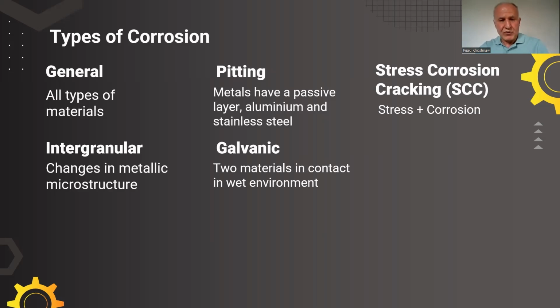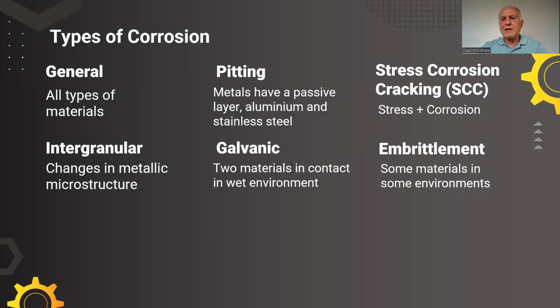Galvanic is a very popular one, when two materials are in contact in a wet environment. Embrittlement: some environments, some solutions cause embrittlement in some materials. Steel is one of them. Embrittlement can come from cold temperature, very cold, minus 50, minus 40, especially in steel. That causes embrittlement, and that causes big problems in some applications. We will talk about this later. It also comes from some elements, for example hydrogen embrittlement or sulfur. So with any solution, for example oil products, which includes these elements, if there is steel in that environment, embrittlement can happen.